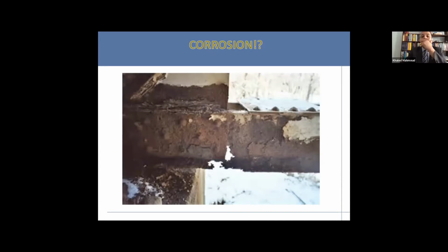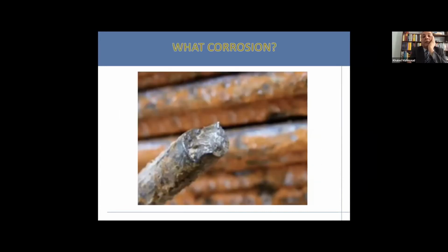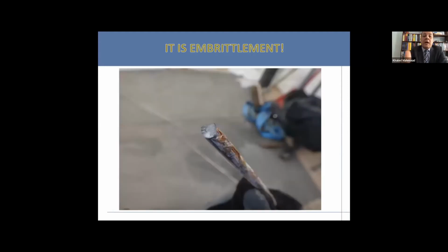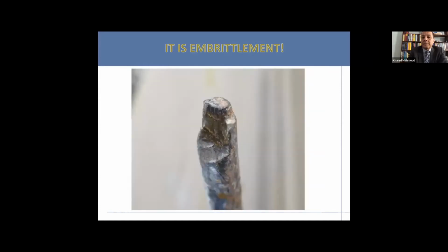But when you look at the wire, what corrosion? There is no corrosion to speak of here. What's happening here is embrittlement. Embrittlement that caused the crack propagation, and further the crack till it reaches a critical crack depth, and then the wire breaks. There are too many examples. You will not find a broken wire that does not demonstrate this form of break in one way or another. This is a brittle break.